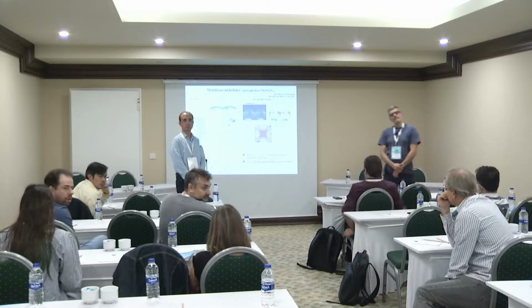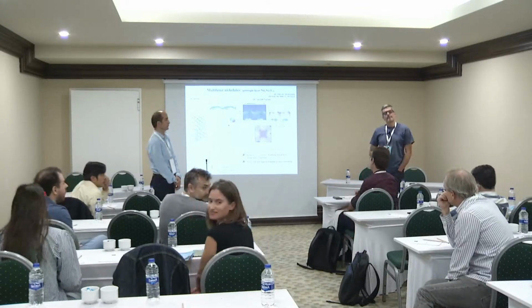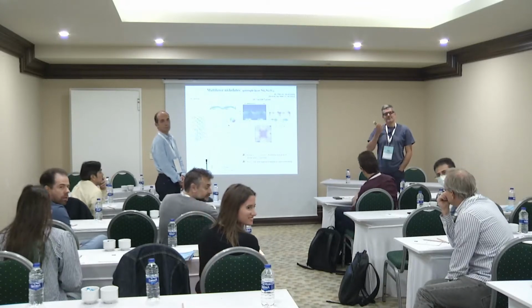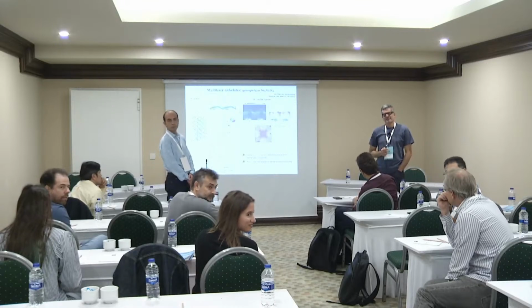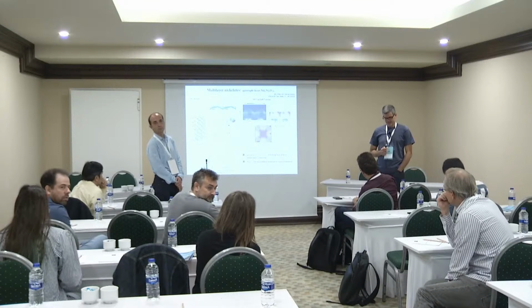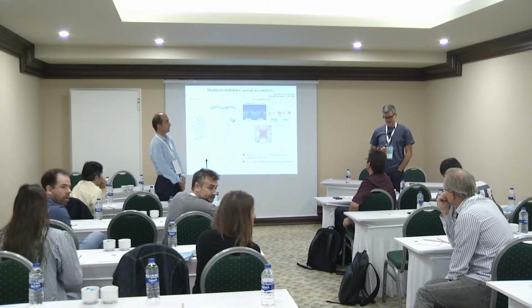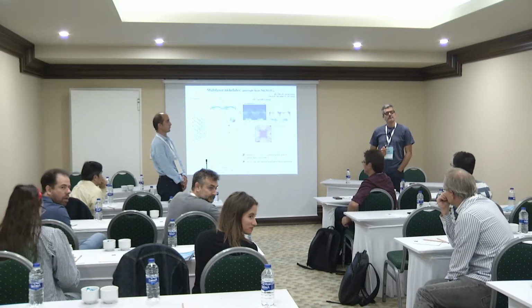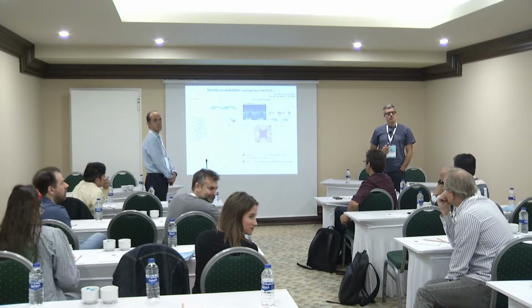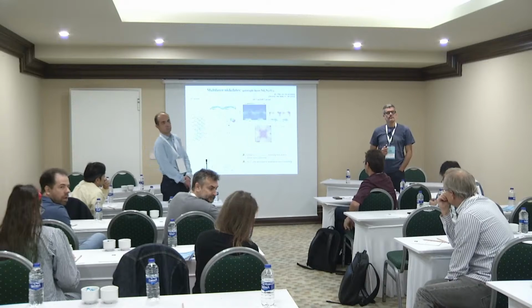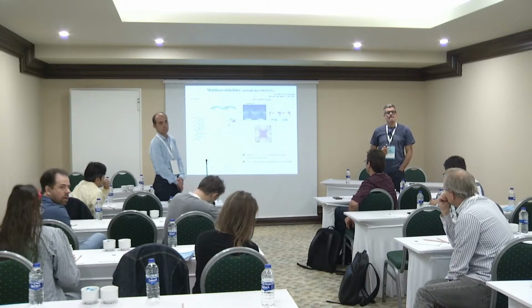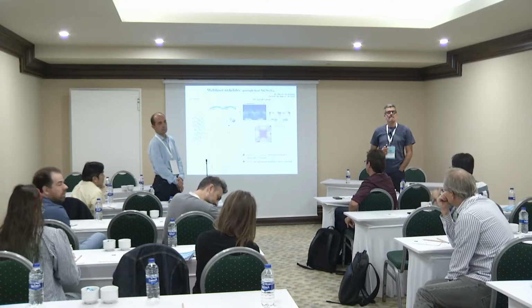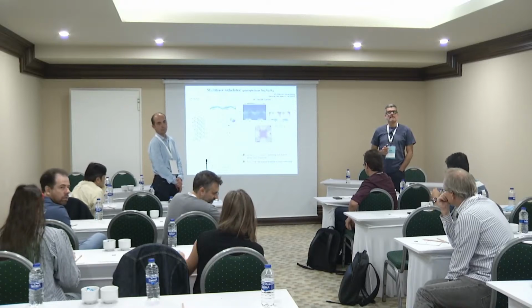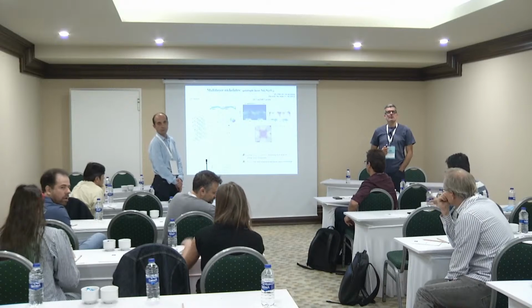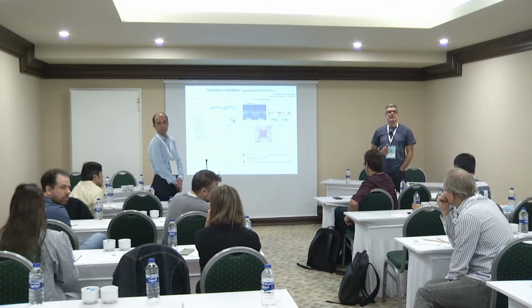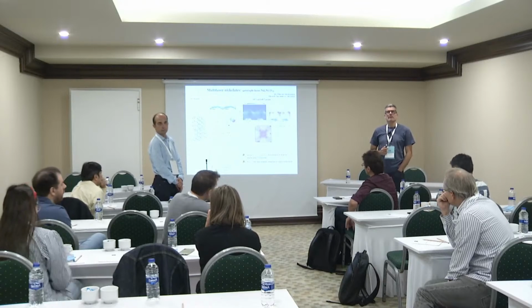Let me please summarize my understanding of nickelates, and if anybody present disagrees, not just the speaker, please say. My understanding is that even though the nickelates are structurally similar to the cuprates, they are in fact more similar to the pnictides electronically. And the main reason for that similarity is that the oxygen ligands are much more passive in the nickelates than in the cuprates, so it is similar to the situation in the pnictides where the metallic conduction occurs directly from iron to iron, and the phosphorus ligands are passive.